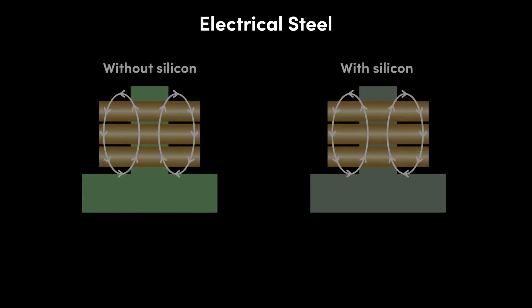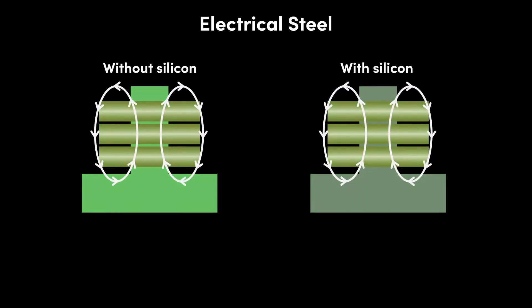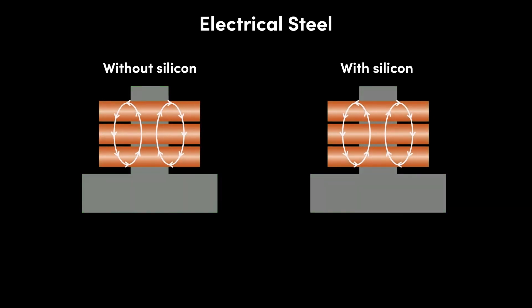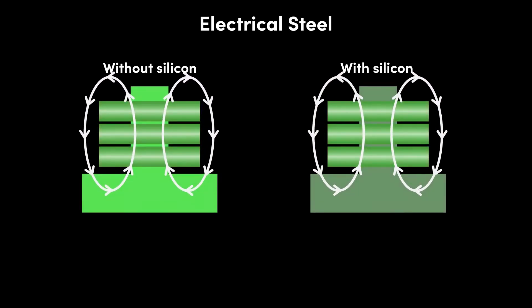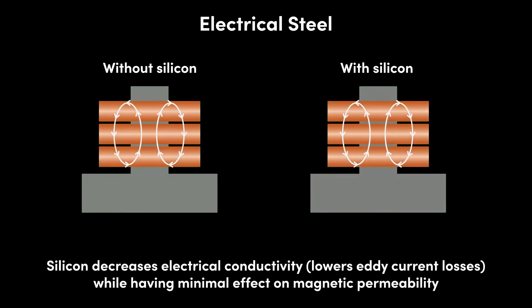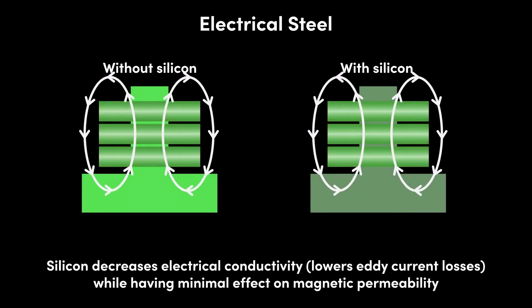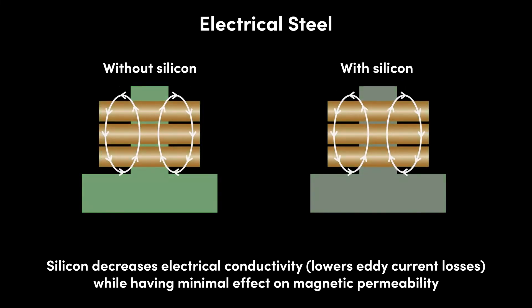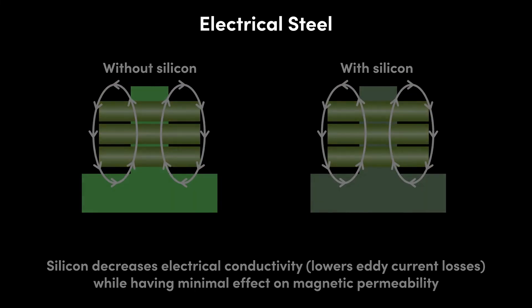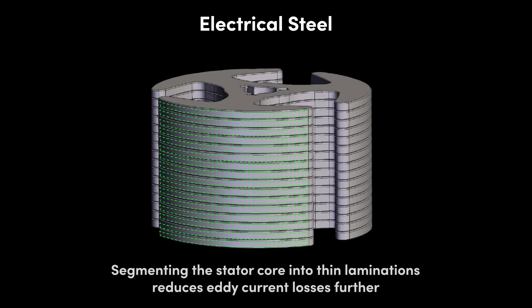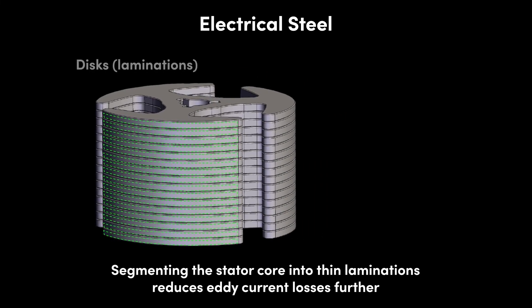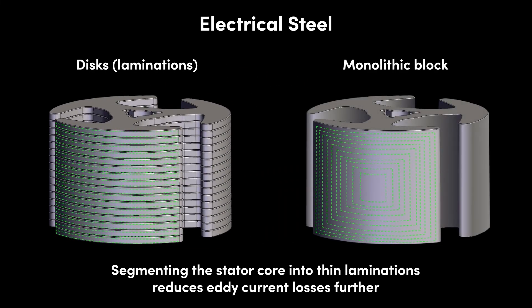In addition to hysteresis loss, we have another type of loss: when a conductor such as iron is placed in a magnetic field, electric current — also known as eddy current — is induced in the conductor. This lowers efficiency of the motor, since energy is wasted as electrical energy trapped in the core material. We call this the eddy current loss. A lot of that wasted electrical energy ends up as thermal energy, or heat, which can damage the motor and cause it to fail. This is why we want the stator core to have high magnetic permeability and high electrical resistivity — we want the stator core to be permeated by the electromagnetic fields, but we don't want induced currents.